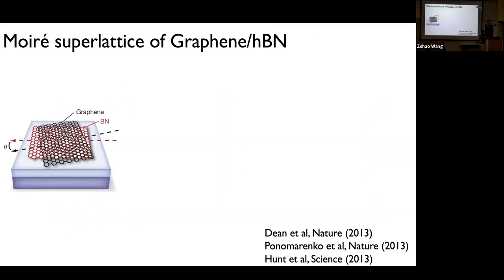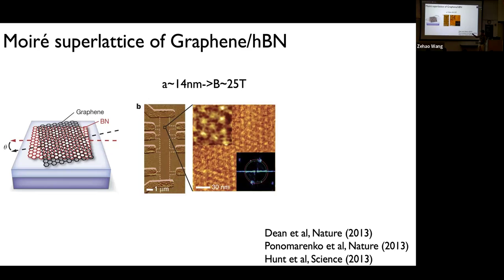One way of doing this is to use a moiré superlattice. The first moiré superlattice that I'm aware of is when you place graphene on top of boron nitride, and because of the close but not quite identical lattice constants of the two materials, you always get a moiré superlattice. There was a series of experiments back in 2013 that looked at this. If you make this sample and look at it under, say, atomic force microscopy, the resolution is not great, but you can see that there is some periodicity. You can create, this way, an artificial lattice with a long wavelength periodicity of 14 nanometers.